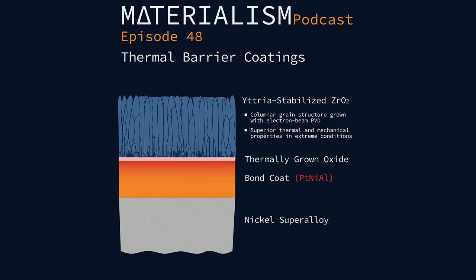Yeah, it's exactly like stainless steel, right? You intentionally add chromium metal. You don't add chromium oxide to stainless steel. You add chromium metal knowing that it will react to form the chromium oxide on the surface. You're essentially getting the same thing. You're adding aluminum-rich bond coat materials, knowing that when it gets heated in air at high temperatures, it's going to form what we call the TGO, the thermally grown oxide.